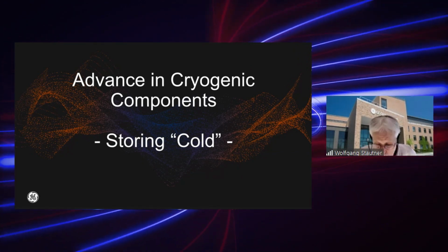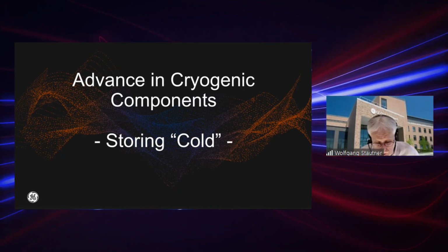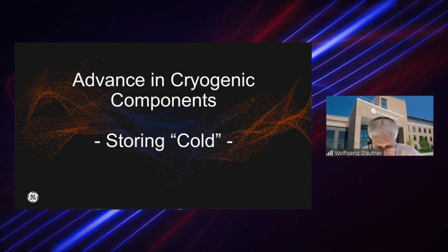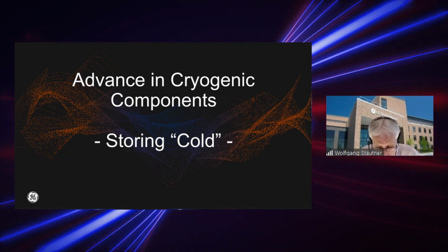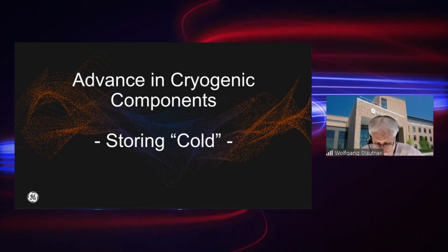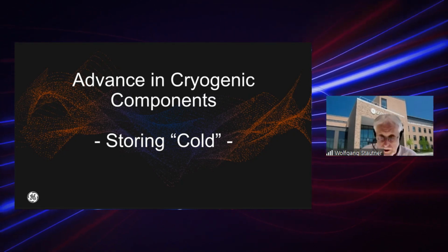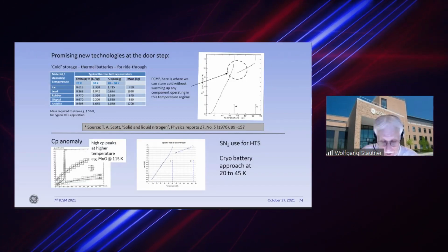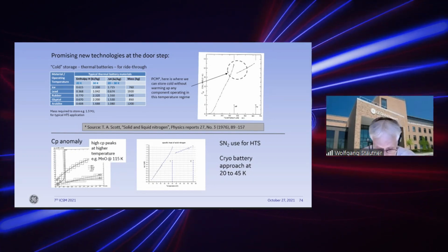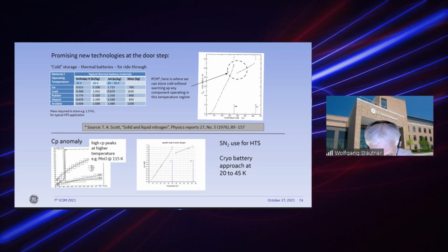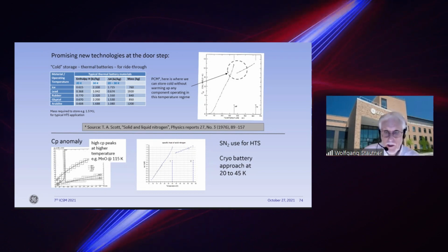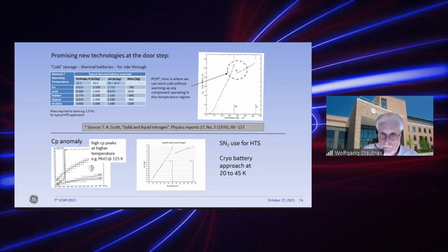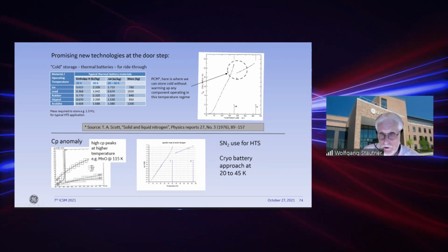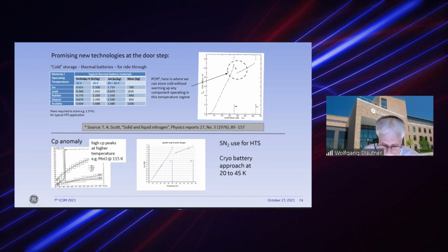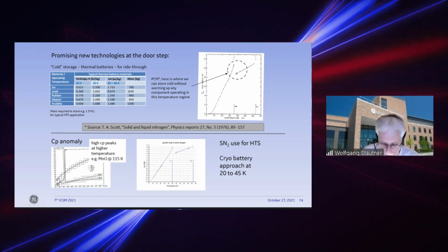Now, we not only need to transfer heat like we do with a heat pipe, but we also need to store cold. And what do I mean by that? Suppose you lose cooling power, or the power of your cooler. What do you do then? You need to keep your cold mass cold to avoid any magnet quench. And it's a difficult undertaking, but very recently some good solutions have been found, as shown in the table, and also from MIT. And we are taking advantage here of a Cp anomaly of solid nitrogen, where we can actually store some heat without warming up the cold mass.